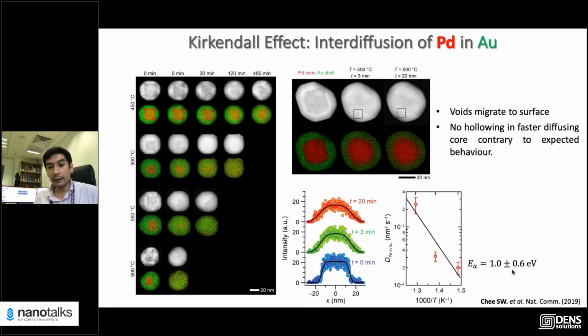And here, same deal. You're doing exactly the same thing. Here you find the activation energy for the diffusion of palladium is lower. So palladium diffuses faster, as you expect. And these numbers are in very good agreement with the literature values. But again, same thing: you have voids forming, right?